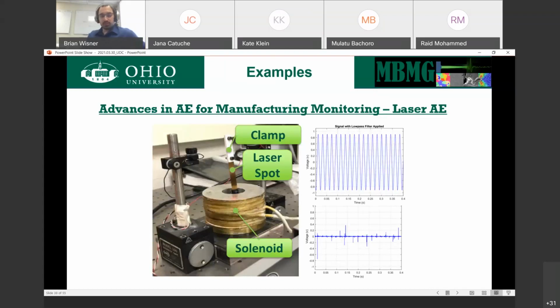So this was developed initially for Air Force research labs for trying to monitor fatigue crack initiation in what they call a free vibration setup. The premise is that your sample is held from fishing line and the load is applied by a solenoid to induce mode 1 bending. And the question is, can we detect when cracks nucleate in this? This is a very thin film sample. So we're investigating this predominantly for turbine blade applications. If we make contact with this, it's not going to be in mode 1 bending anymore. It's not going to fail the right way. We're not going to see what the material is doing. We're going to see what the structure is doing, what the system with the sensor combined is doing. So we want to try to see whether or not we can do this with a laser.